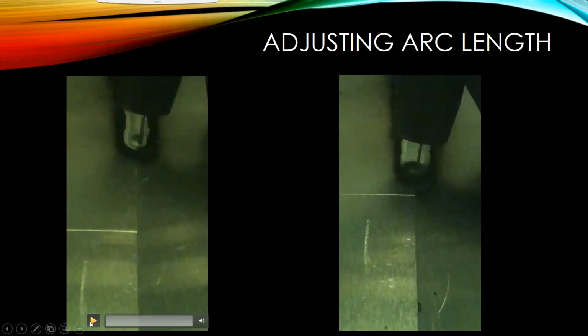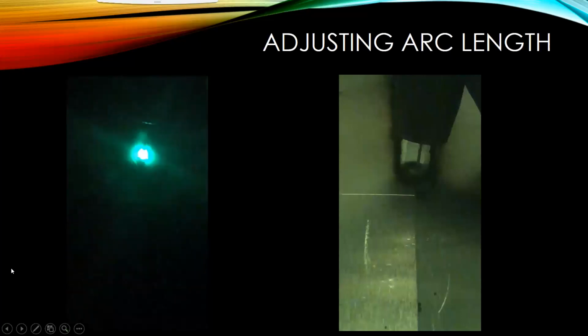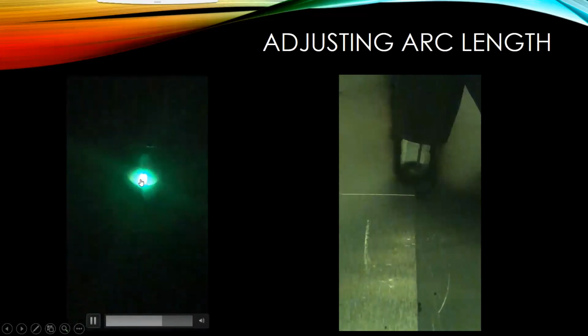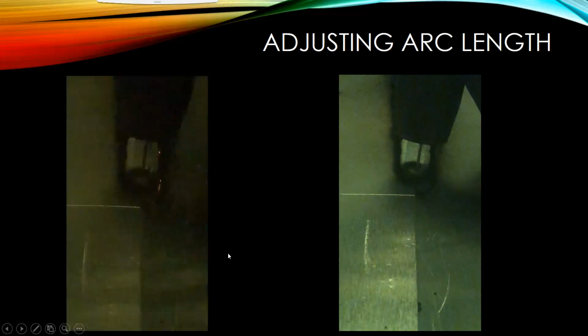So I got two videos here. The first one's just going to be like a pretty tight arc length, and then basically with the adjustment on the front of the machine, I increased it for the second video. So let's watch the difference there. So you can see pretty tight, which depending on the joint that you're going to be welding, you may want to adjust that so it's to your benefit. Now you can see that arc length lengthened, longer distance from the end of the wire to the puddle itself.